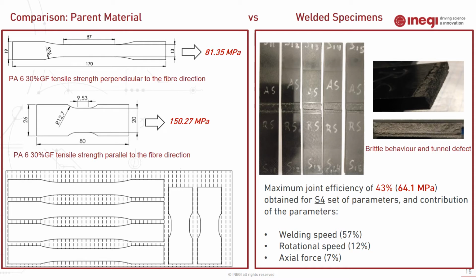And in this slide, the comparison between the parent material and welded specimen is shown. As you can see on the left, the tensile strength of the parent material in both directions, parallel to the fiber direction and perpendicular to the fiber direction, and the maximum joint efficiency of 43% obtained for the S4 specimen. The welding speed with 57% contribution had the highest contribution, followed by rotational speed for 12% and axial force.